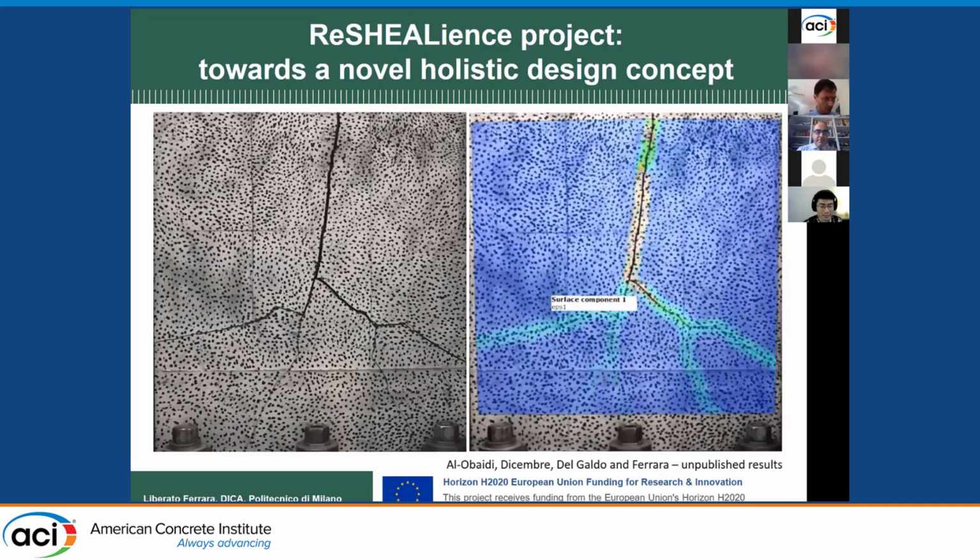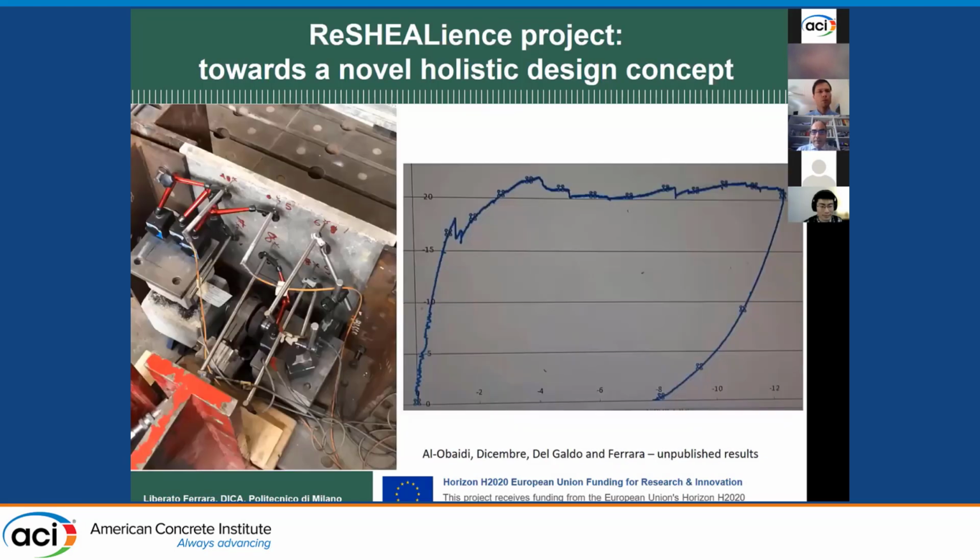And this is a picture from the top of our setup and a curve. Actually, this is not an elaboration. Tests were performed this week. So this is a picture of the morning in the lab, and you can see the remarkable plastic behavior of the slab up to a deflection limit of 10, 12 millimeters, which means about 1/3 of the thickness.